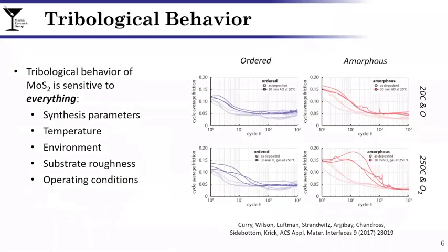So despite the use of MoS2 and the great promise for many different applications, design of MoS2-based systems is difficult because tribological behavior of MoS2 depends on, well, like everything. It depends on temperature, it depends how it's synthesized, the environment. It even depends on how rough the substrate is. Shown here is just one example where you're looking at friction on MoS2 deposited in different ways and in different atmospheric and temperature conditions. And you can see a vast array of frictional behavior. This is a challenge when using or planning to use MoS2 as a lubricant.